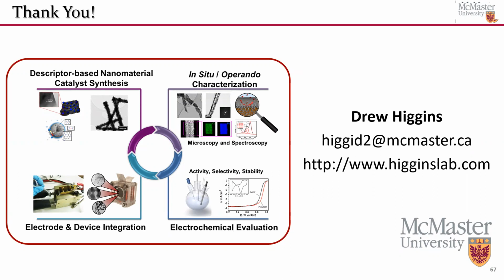So I work a little bit with lithium metal batteries, and I know people, for example, in these sort of organic systems often use lithium metal as a reference electrode, even though it doesn't work very well as a quasi-reference electrode. And there's been some recent recommendations to switch to something like lithium iron phosphate. I was just wondering if there's a way to predict what materials would behave well as a reference electrode if you're working in a system where you can't really use conventional materials and you have to use these quasi-reference electrodes, or if you kind of have to just do trial and error and see what works.